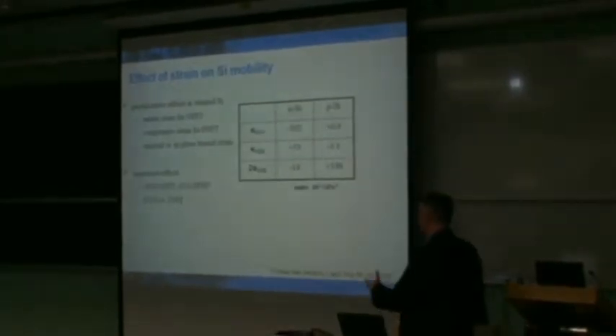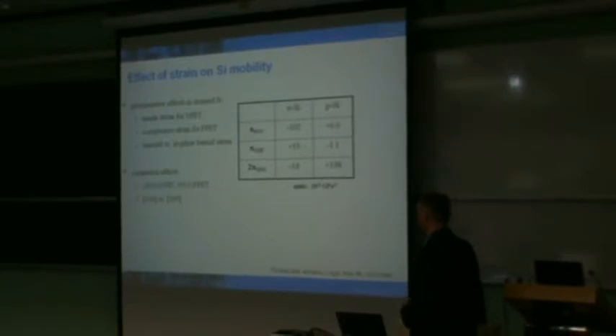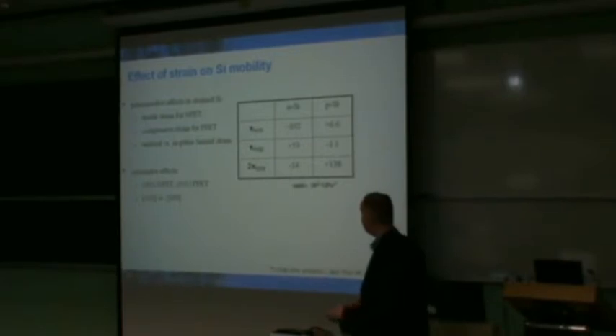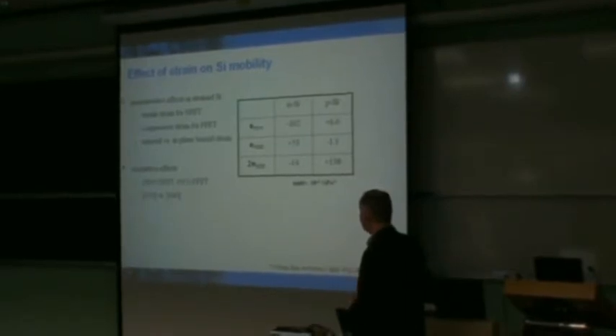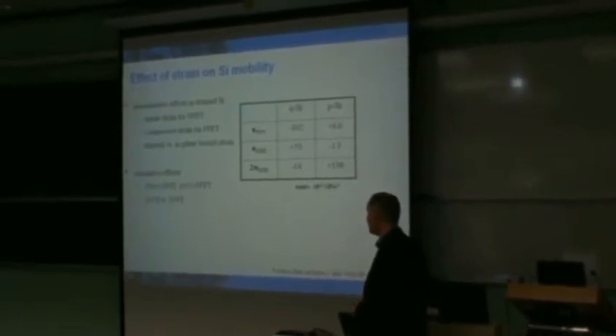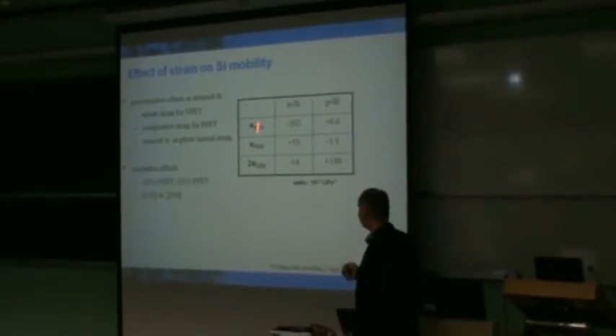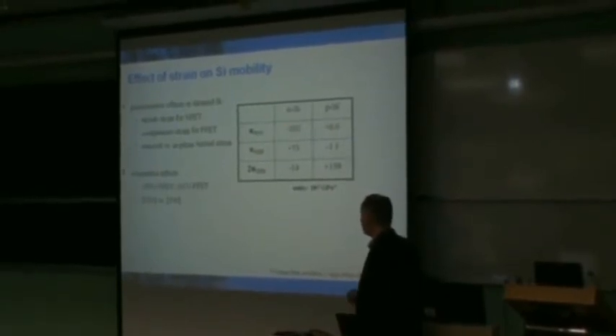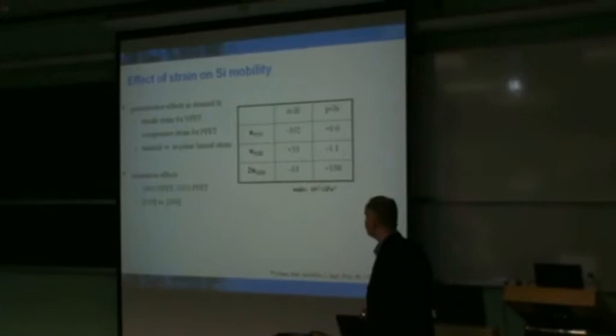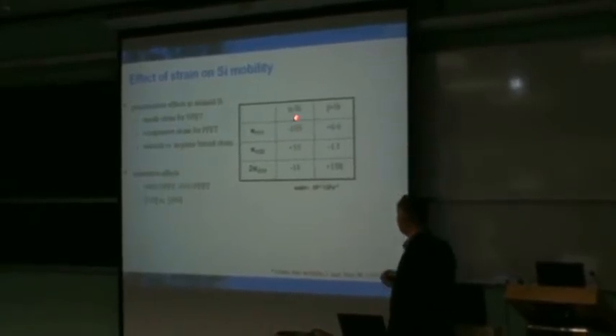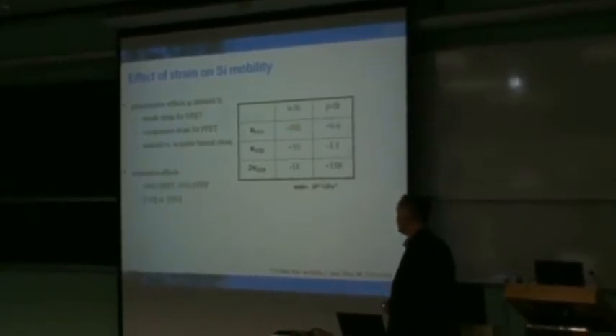There are metrics that have been developed to help understand and quantify this change in the behavior based on the stress field within the system. And we've learned heuristically about which types of strain are beneficial for that process. And what I'm showing here are just the three independent components of the piezoresistivity tensor for your N-type silicon as well as your P-type silicon.